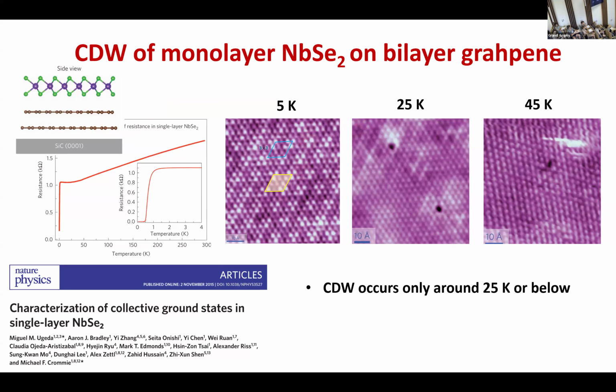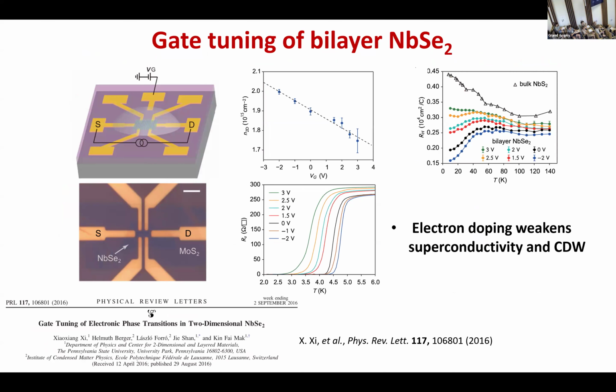And they claim it's opposite to the other one. So from the exfoliated samples, the charge density wave is enhanced. But here, from STM, they directly measure that they observe that the charge density wave only appears below 25 K, which means that, for example, in the picture in the middle, you don't see these brighter spots for every 3 atoms. But then you see this only at 5K. So apparently there is something like contradicting each other. So I also talked to one of the authors, Xiaoxiang Xi, just recently, and he thinks this is still not really clear. But I think from his experiment back then, in 2016, there is some hint. Maybe it can explain a little why.